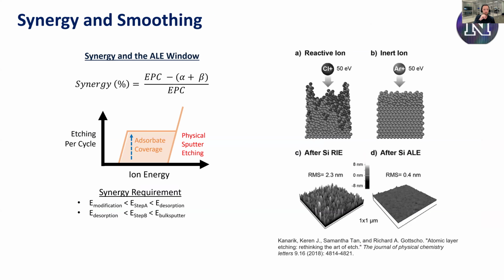Typically, we see what we call the ALE window as a function of ion energy. As we increase ion energy, as long as we have enough adsorbates, enough of a modified layer to modify the whole surface: at first, if your ion energy is insufficient to remove that modified layer, you don't see any etching. Then, when you have enough energy to remove that modified layer, but not to do any kind of bulk sputtering or physical etch, you see hopefully a nice flat region, we call it the window region in your process, where the etch per cycle is pretty constant. Then when you get to a high enough ion energy, you get into a physical sputtering regime.